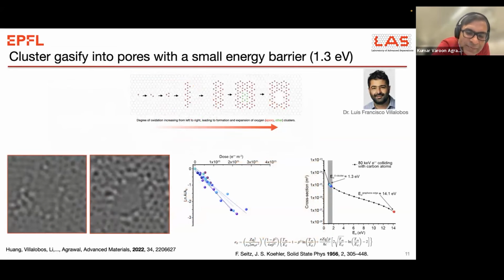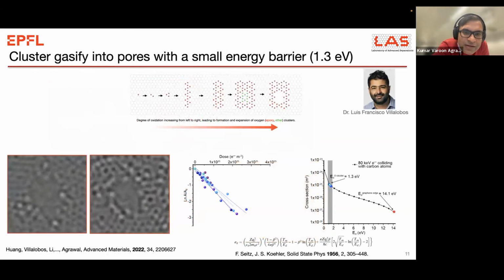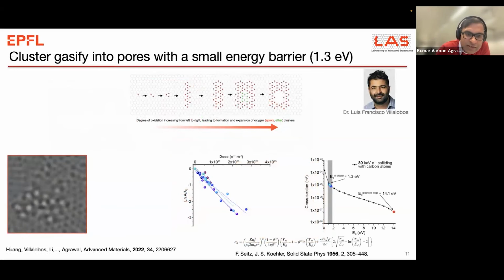Just to show you how the hole forms, this is an experiment we did in a transmission electron microscope. In the microscope, you can suspend the graphene and oxidize it all the way to this step where you have not necessarily formed a hole, and then you can expose it to the electron beam. Once we do that, we see a hole forming at the center of this cluster. We can look at the size of that hole as a function of the dose. We see a linear correlation between the size of the hole and the dose. This says the size of the pore can be controlled by the amount of energy that we give.